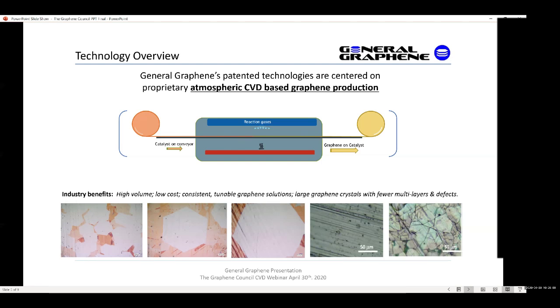Generally, we utilize metal foils up to 300 millimeters wide in continuous lengths and spool it roll to roll, similar to what you saw before. In short, during our process, we prepare, etch, and anneal the foil substrates, encapsulate the foil in a proprietary enclosure system, and then send the system through the equipment at high temperature, during which a mix of gases, including hydrocarbons, contact the surface and initiate the single or multi-layer graphene crystals.